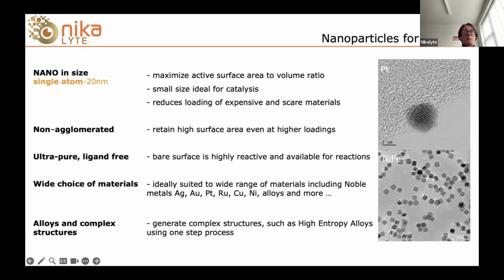Also, they're non-agglomerated nanoparticles. That's important because it means that each nanoparticle is active and isn't lost in a bulk agglomerate. And that ultra-pure surface that I mentioned at the beginning, the fact that there are no other chemicals on the surface means that that surface is available for reactions and could be potentially more reactive than an equivalent nanoparticle generated by another technique.